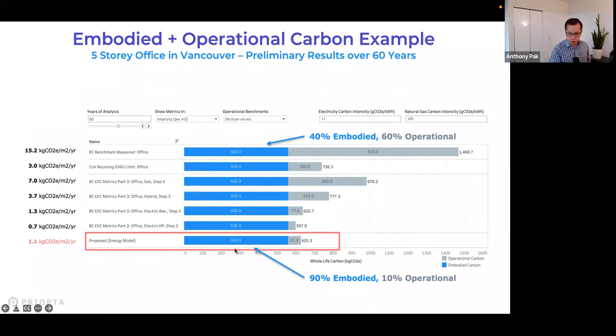You can see the embodied carbon is about 558 kilograms of CO2 per meter squared. But then we compare that with the operational carbon emissions over 60 years. And it depends on what you're comparing against, obviously, because we're in the design phase. So with our energy modeling results, we can see right now, even over 60 years, the operational carbon emissions have come down so much, it's 90% versus 10%. However, if we compare it against the typical office building, this is based on actual measured performance, even then, it's still about 40% after 60 years, right?